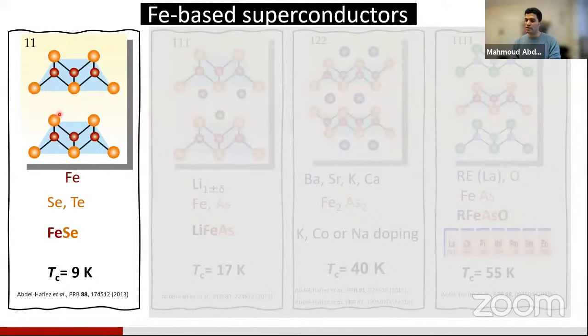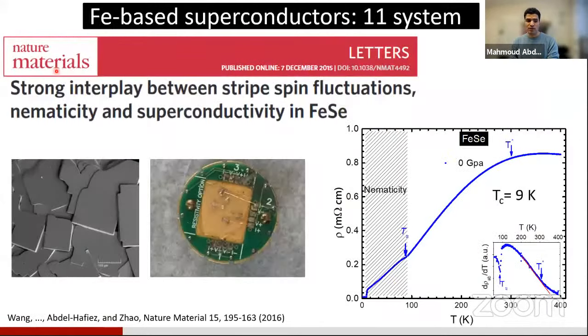So let me show you one example about 1-1 system. Just 5 years ago, we tried to work on this kind of 1-1 system, iron selenium. And we were able to grow high quality single crystals and even to measure the transport and also to measure the neutron on these kinds of materials.